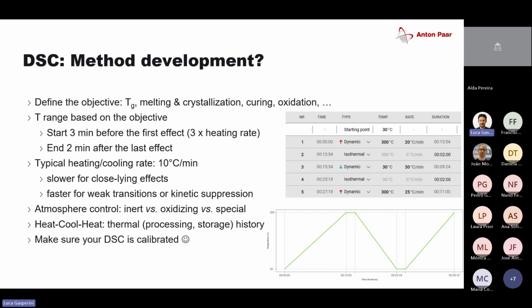Typical heating or cooling rate that is being used in a DSC. In the past, I was very evasive when someone asked, so what's the typical heating rate in a DSC? I was like, that depends on how much sample you have and on the application and on the ranges and if it's a strong effect or weak effect. And there was like an hour discussion on what should be the heating rate. Now I'd say 10 degrees a minute, you're good. It's like a golden rule in DSC. If you don't know, this is something that we usually work with.